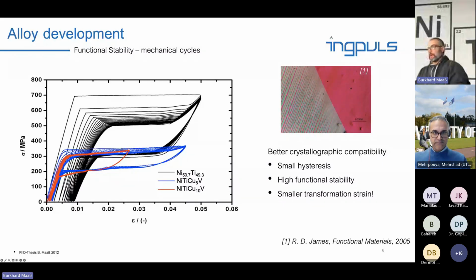But there's also one thing that you learn. You see the strain which I can reach with the material with less copper and the strain with the material with 10 atom percent copper. It's almost half. So you pay a price. The hysteresis is small and the functional stability is really high, but as austenite and martensite are so compatible, the transformation strain becomes smaller. And so you see that there's not one factor which determines if this is the best material. The best material needs to be the best material for a certain application.